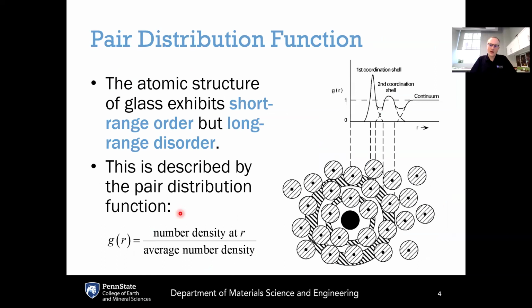Now, one of the ways that we can characterize the order or disorder of a material based on its atomic structure is using a function called the pair distribution function. So the atomic structure of glass, what we're going to see is that it exhibits short-range order but long-range disorder. And one of the ways to quantify that short-range order and long-range disorder is using the pair distribution function, which is commonly represented by this function g(r), where r is the radius from some central atom.